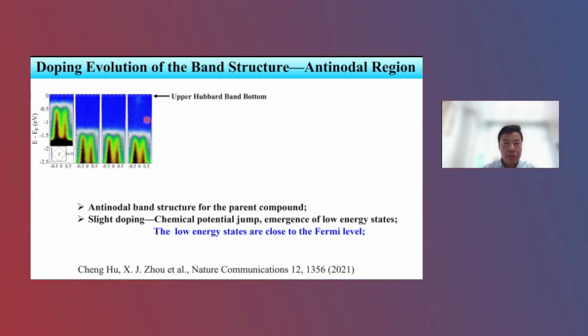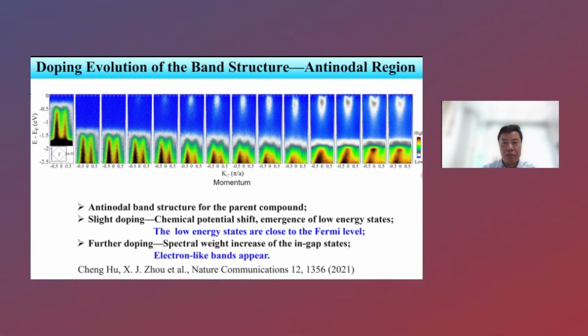Okay, then actually here you can start to see this area. You start to see something already reached the Fermi level, the Fermi potential. So this actually is the upper band bottom. Then you increase the electron doping further, you can see these electron states near the Fermi level just stronger, stronger, stronger, eventually form some electron-like bands here. Okay, when you reach about 12%, you can see clearly an electron band here.